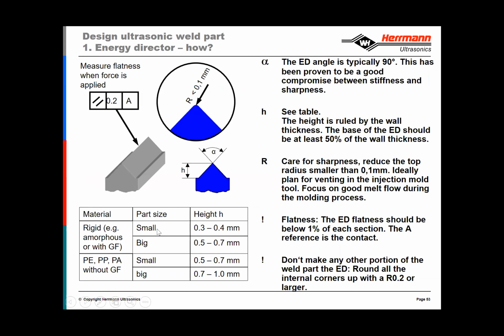And then the height of the energy director is primarily tied to the size of the part. And I mean, although there's not a clear definition of what a small part is or what a large part is, use your judgment there. In a small part, we'll see energy directors in the range of 0.3 to 0.4 millimeters for amorphous resins. And for a small part for semi-crystalline resins, we'll usually see a little bit larger of an energy director, 0.5 to 0.7. And then large parts, amorphous resins, 0.5 to 0.7 millimeters, or as large as 1 millimeter for large semi-crystalline parts.